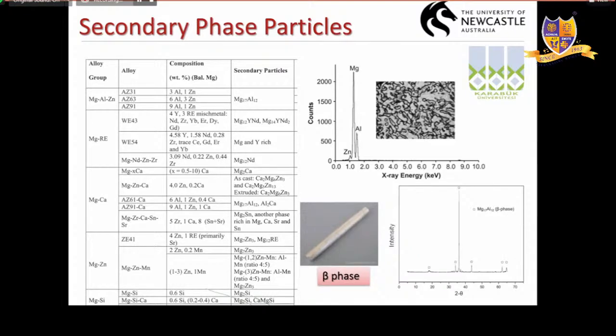So what we did was create what we call the secondary phase particles. I said producing a magnesium alloy is difficult. Producing secondary phase particles is much more difficult. So this was done in collaboration with Karabuk University in Turkey, who specialize in manufacturing and producing these intermetallic particles. A PhD student from that university visited my lab with this intermetallic sample, and we did some testing on those alloys.